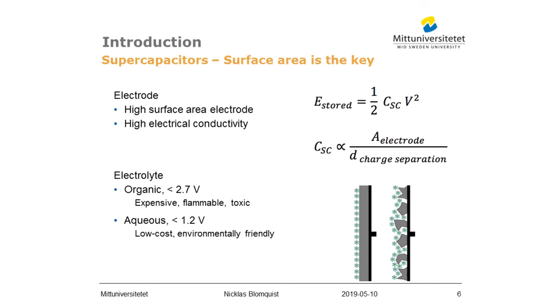The electrode material in a supercapacitor needs to have high surface area to have a high capacitance. And as you can see in this equation here, the energy stored in the supercapacitor is proportional to its capacitance times the voltage squared. The capacitance itself is proportional to the surface area of the electrode divided by the charge separation distance. And this distance is really small, it's in nanometers.